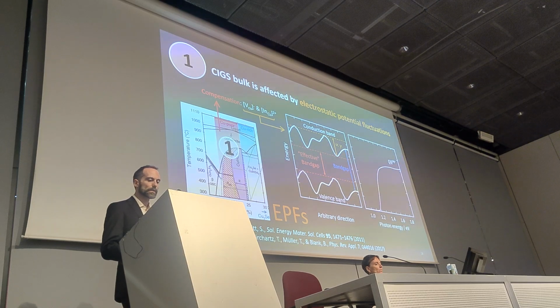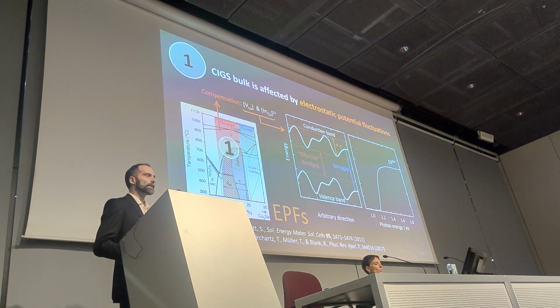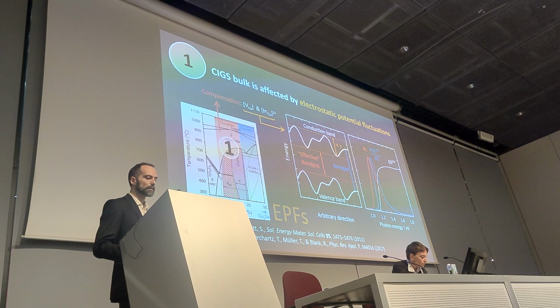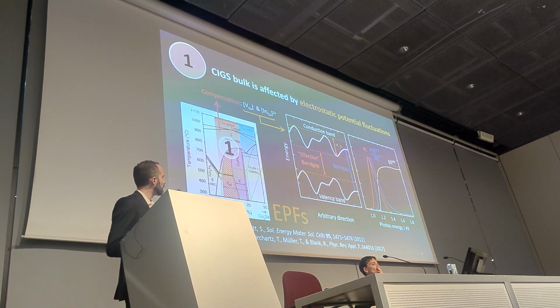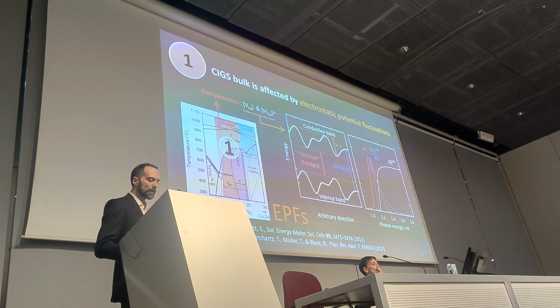This has consequences also in the optical signature of the material. Effectively speaking, we don't get a step function, but we have a broadening of the absorption onset known as Urbach tailing. And we also have, if we compare the first derivative of the absorption onset with the photoluminescence, the peak of the photoluminescence emission, a redshift of this peak.